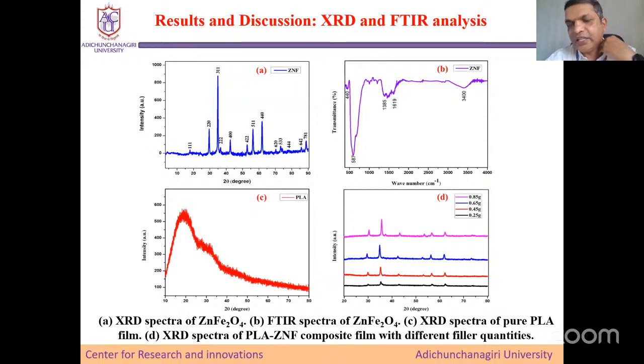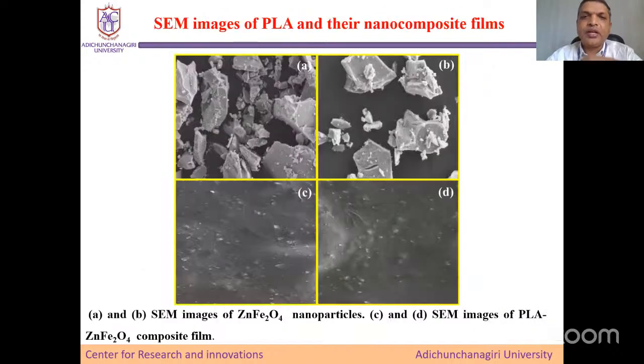And this is the XRD of PLA, which is completely amorphous. At the end, you get the 2 theta peak which corresponds to ZnFe2O4. That indicates the presence of ZnFe2O4 in the polylactic acid. Of course, it is not altering the crystallinity of the material, but it is altering the texture, not the crystallinity. You see here, this is the ZnFe2O4 nanoparticles, and the bottom figure indicates the same image of the PLA, ZnFe2O4 filled nanocomposites.